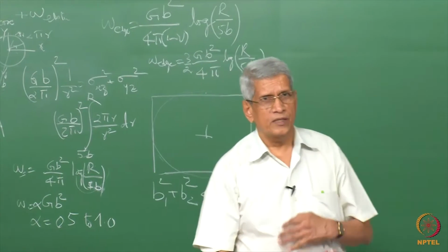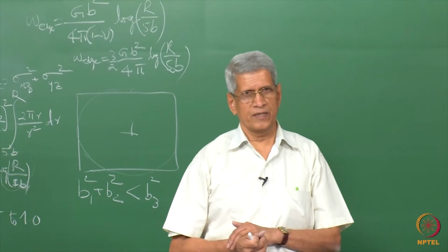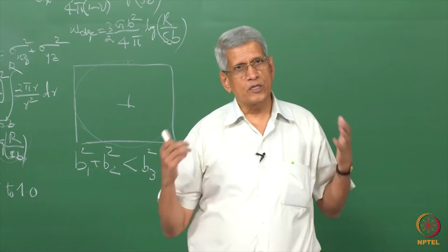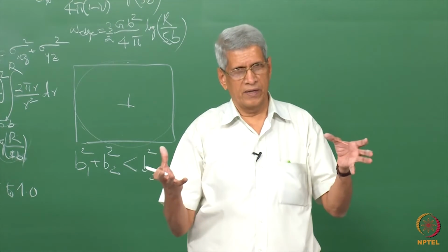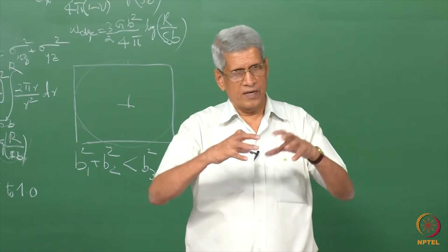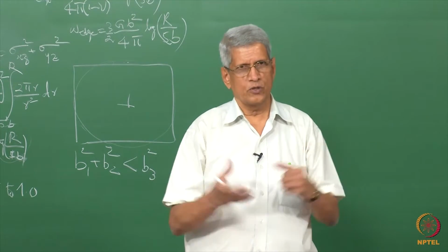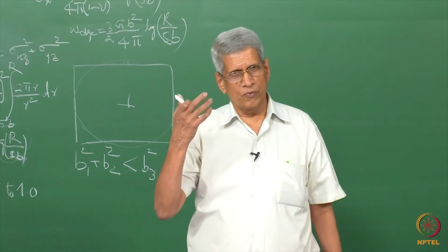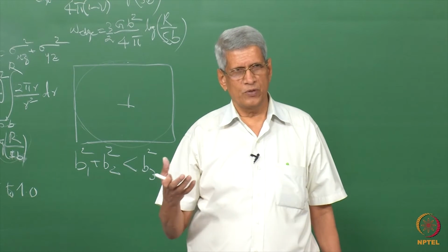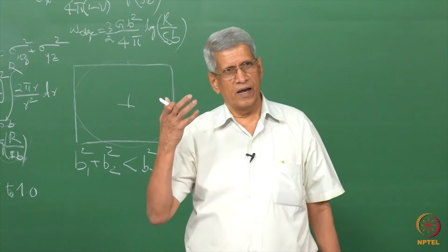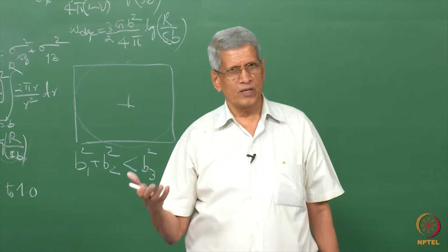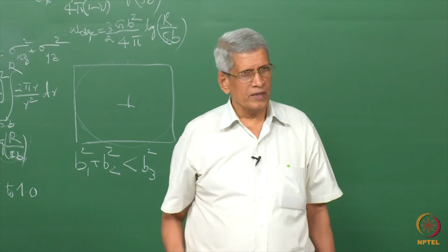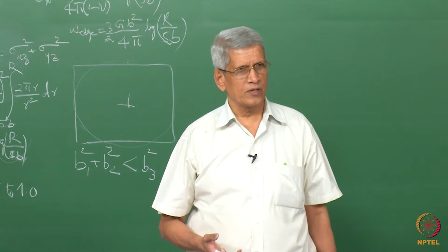This is per unit length. What happens is the increase in energy per unit length. This turns out to be the force, which you call the line tension, like a soap bubble. It has some area associated with it, and it tends to shrink. So the same energy which we use as the surface energy of the bubble itself, we use to represent the force also, as surface tension.